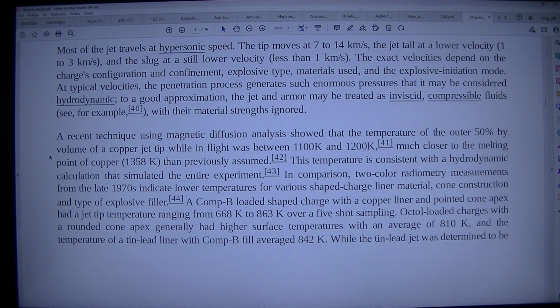In comparison, two-color radiometry measurements from the late 1970s indicate lower temperatures for various shaped charge liner material, cone construction and type of explosive filler. [44] A Comp B loaded shaped charge with a copper liner and pointed cone apex had a jet tip temperature ranging from 668 K to 863 K over a 5-shot sampling. Octol-loaded charges with a rounded cone apex generally had higher surface temperatures with an average of 810 K, and the temperature of a tin-lead liner with Comp B fill averaged 842 K.